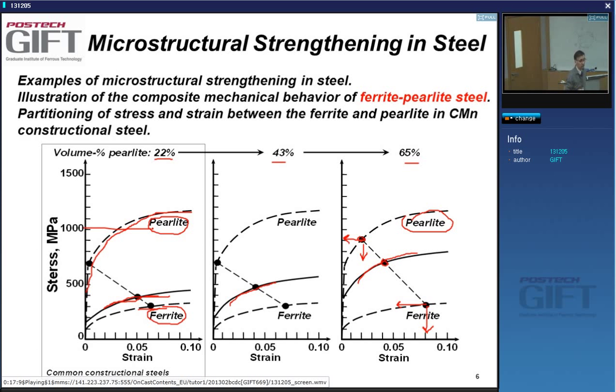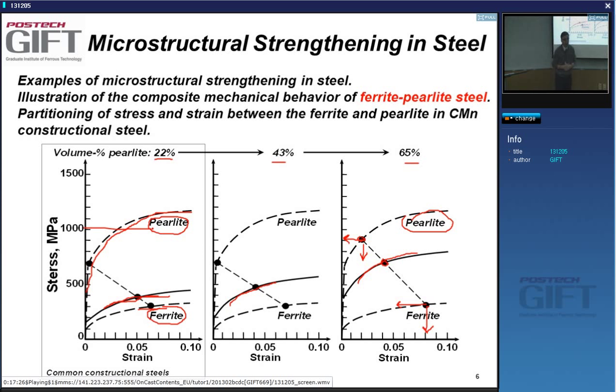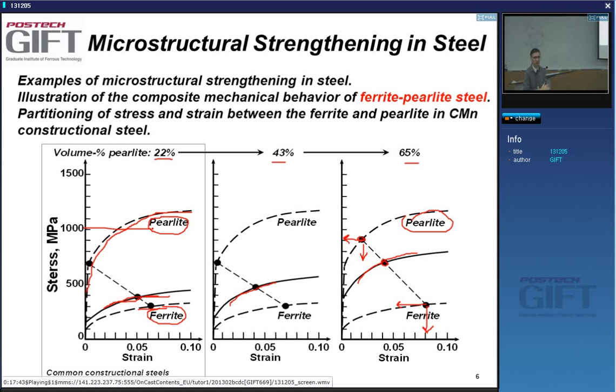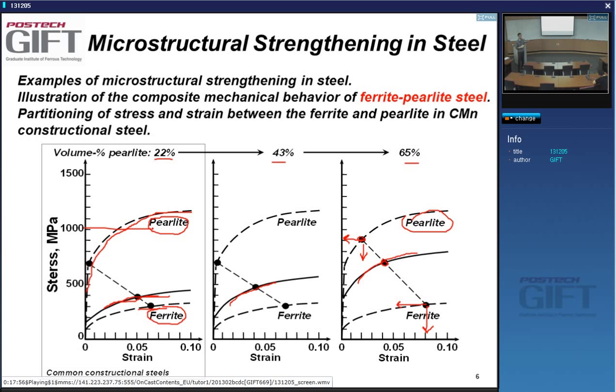The trouble with pearlite steels is that the amounts of strain you can get are limited. The cementite does deform, but not that much — 10 to 15% is about the limit before even the lamellae eventually break. You cannot really make car panels with them because formability is not excellent. Additionally, you have to add carbon, which puts limitations on welding. So pearlite steels are a good solution as long as you don't need to weld or do forming. The application possibilities of ferrite-pearlite steels are not that wide.